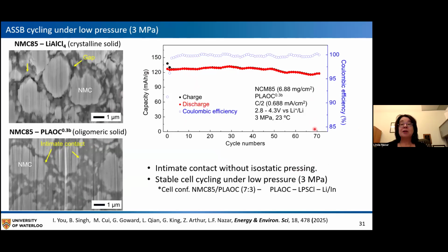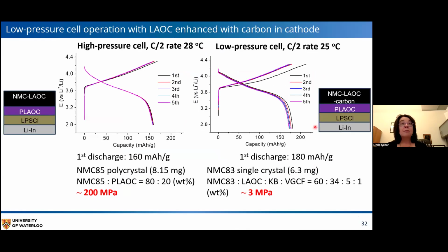And so this, we believe, is really quite hopeful. And it is also of interest then to compare the high pressure cell at 200 megapascals with the low pressure cell at 3 megapascals. And you can see that the first discharge here is even higher, capacity of 180 versus 160 for the higher pressure cell.